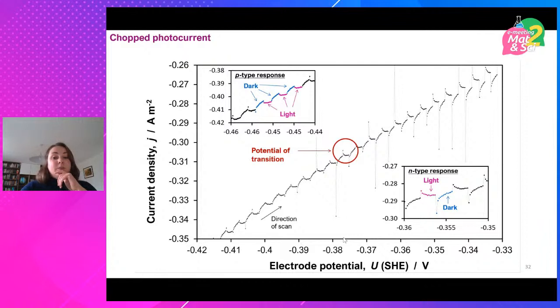So we became quite convinced that this transient method was probably the most appropriate. And perhaps instead of doing it manually, this is something that could be done with a lock-in amplifier. It also gives a photocurrent which is in no way a steady photocurrent, but it will give a very clear transition from cathodic to anodic behavior. So this is something that we converged on as being a particularly useful technique to use, and also simpler than the Mott-Schottky method.